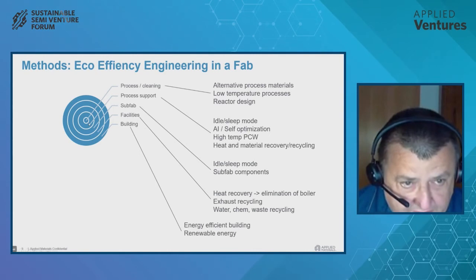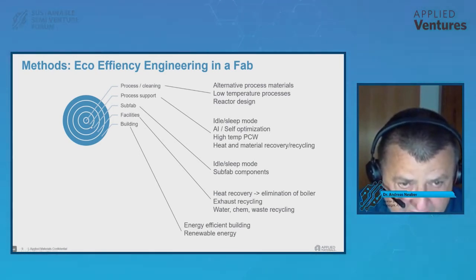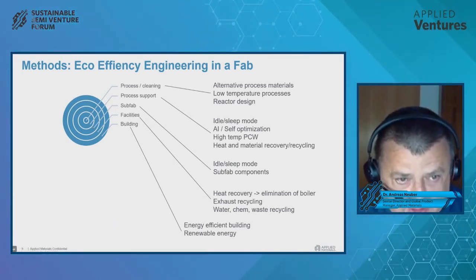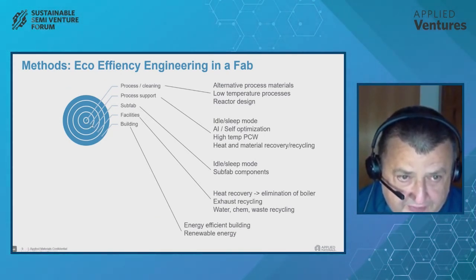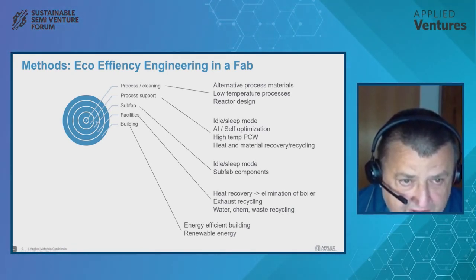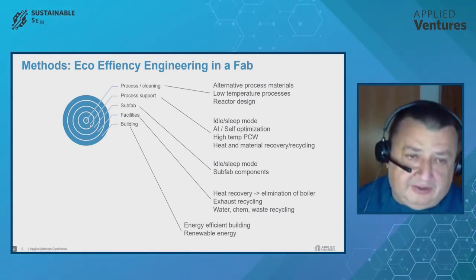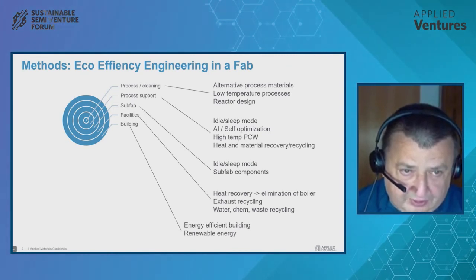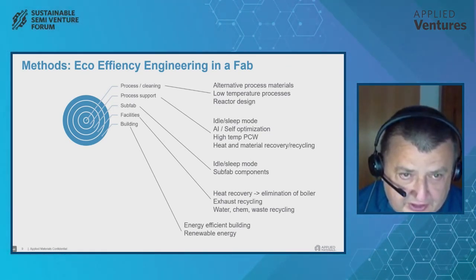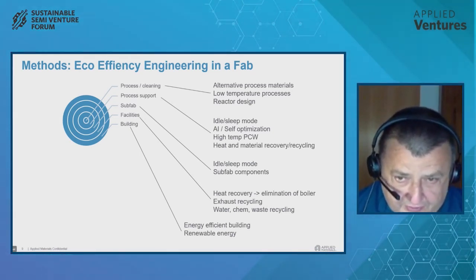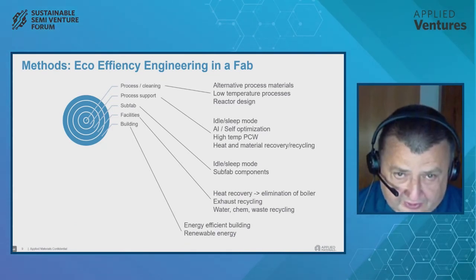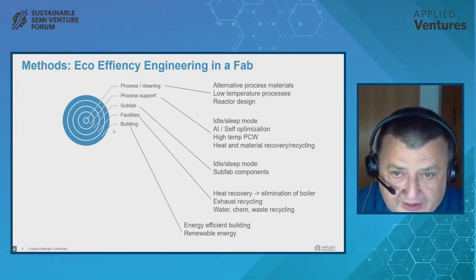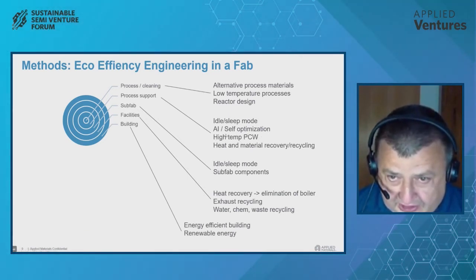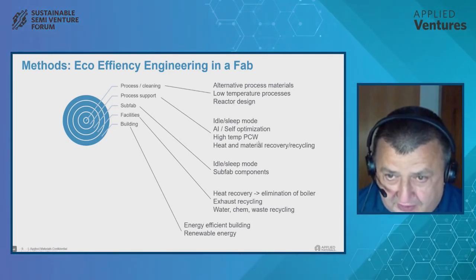Traditionally we are using a process cooling water set at 17 to 20 degrees C. This water was needed in the past to dehumidify the air in the lithography process. But actually, a lot of the processes are running at 50, 100, up to 900 degrees C. If I could, instead of using a 17 degrees C water, use a 35 degrees C water, I could eliminate a chiller. The chiller is turning the temperature from the cooling tower from 35 to 17, so it consumes a lot of electrical energy. They're actually the biggest energy consumers in the fab. So with that chiller's elimination, by changing its process cooling water temperature, we could actually enable a major change.